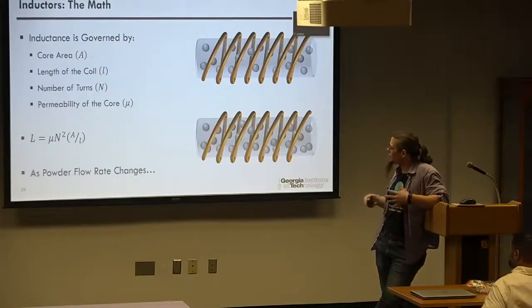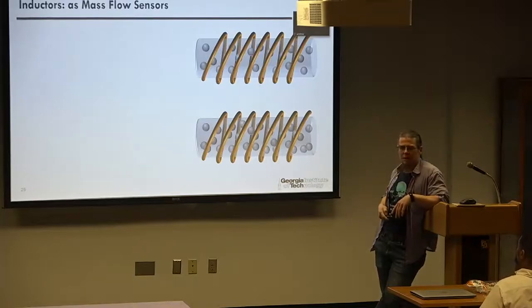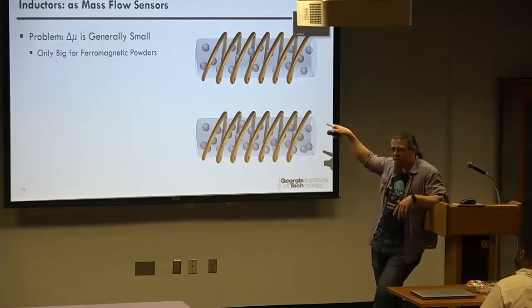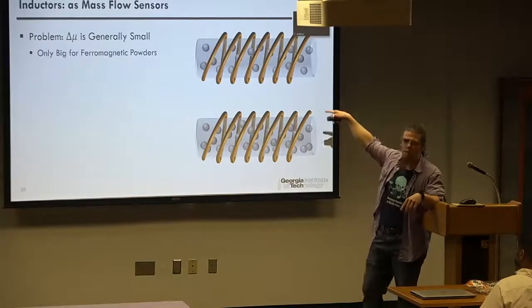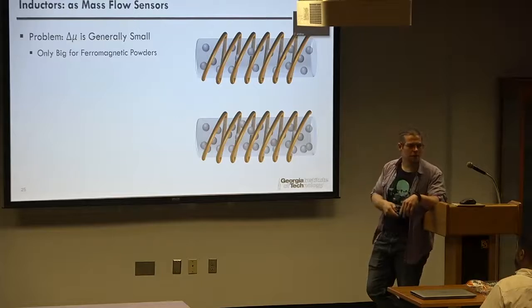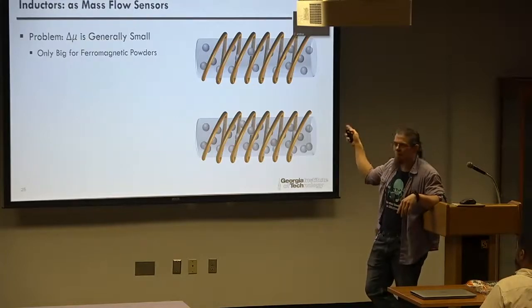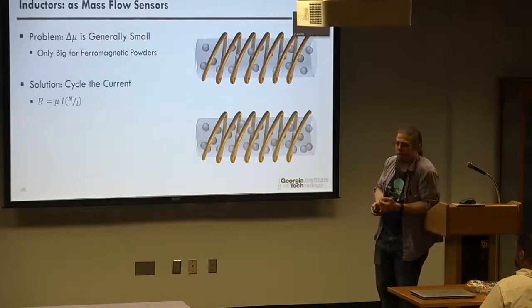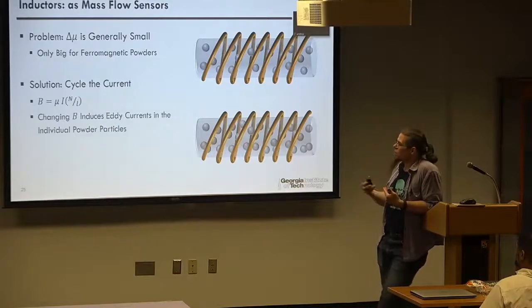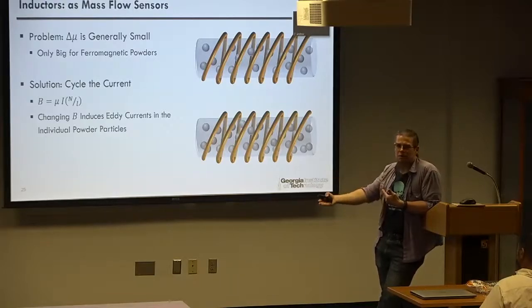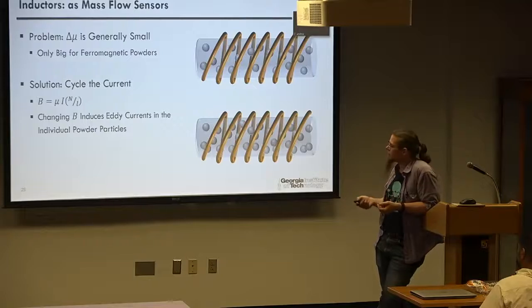It's a material property. As powder flow rate changes, well, not exactly what we expect. We have a problem. This change in this magnetic parameter here is generally very, very small. It's only going to be significant for ferromagnetic powders. So we can't actually use the same method that we did with capacitors if we want to play around with inductors. The solution here is to cycle the current. If we cycle the current, we're going to create a changing magnetic field. A changing magnetic field is going to induce eddy currents in the powder particles, which means that we're going to have a magnetic field produced in the powder particles that combats the magnetic field that we're generating. That's something we can measure. It's independent of whether or not we're ferromagnetic. So that allows us to play with pretty much every metal powder we want.